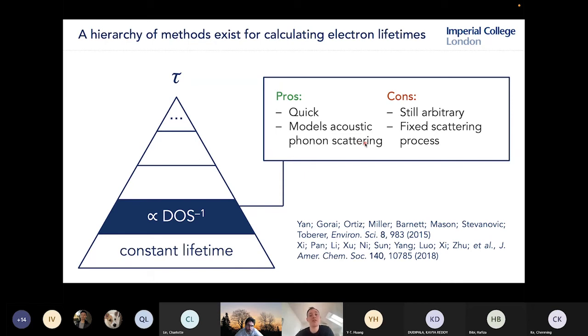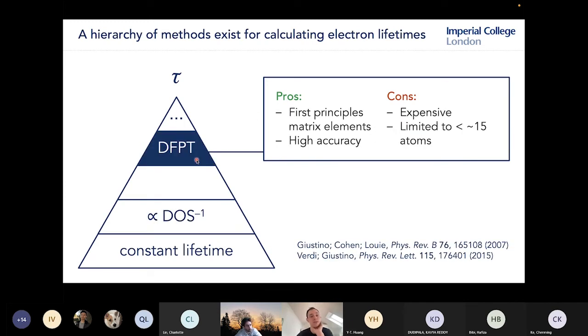But again, you still have an arbitrary element, because you still have to choose the reference lifetime from which you scale your scattering rates. And if you use this approach, you're deciding in advance that acoustic phonon scattering is dominating in your material, and you're imposing a scattering mechanism which might not be correct. On the other end of the spectrum, we have methods based on density functional perturbation theory combined with Wannier interpolation. These are really state-of-the-art approaches, which have been developed in the last 10 years.